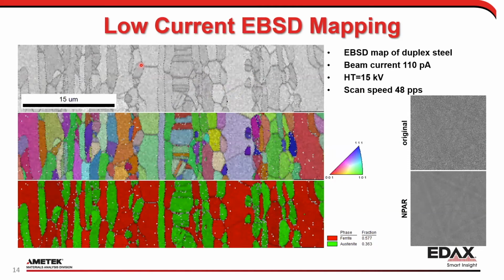You can see that at 15 kV beam at 110 picoamps and 48 patterns per second, this has very little problem doing anything here. The difference here is you can see again the pattern quality. The patterns earlier today you guys saw were bad. You can already see the lines here. This is perfectly indexable data. NPAR, of course, makes it even better.